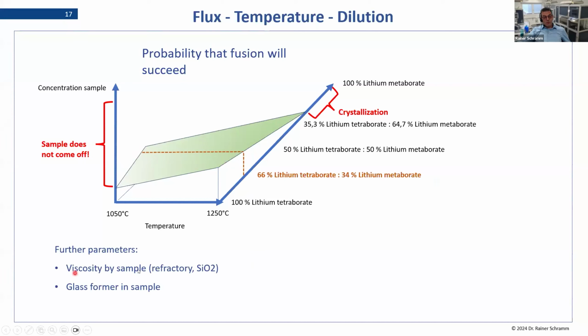Okay, there are further parameters like the viscosity, which is of course defined by the temperature and the material, your sample. So if you have a refractory or a pure silicon oxide, it's a very high viscous sample. You need a very high temperature to get this homogenized. So this is also important. And of course, there will be the question, in this range, when you have not much tetraborate as a glass forming agent, of how much glass former your sample might contribute to your melt. For example, the best is if you have high silicon oxide samples if you want to use this flux, because then a part of the glass former is coming from your sample. So this is also an influence you have to take into account.